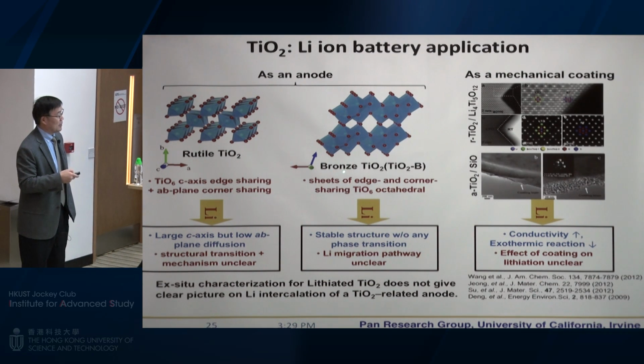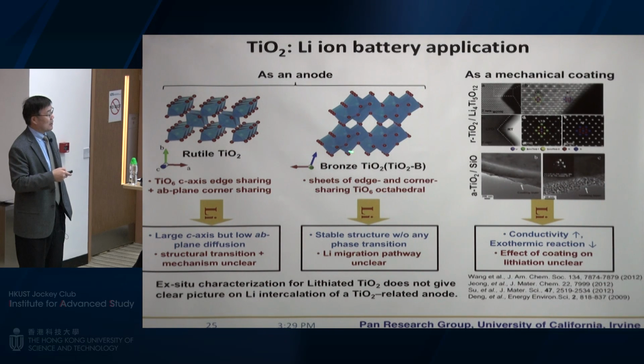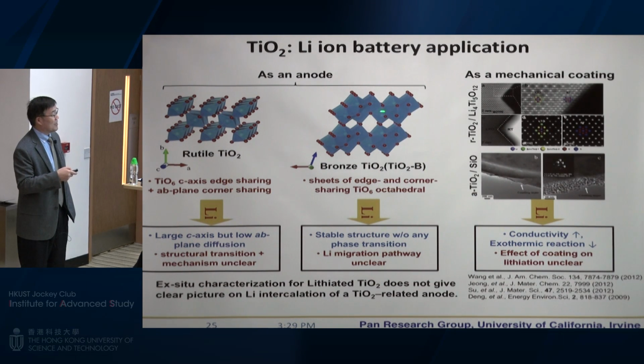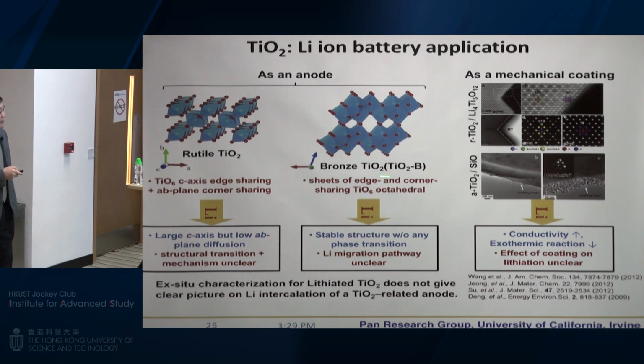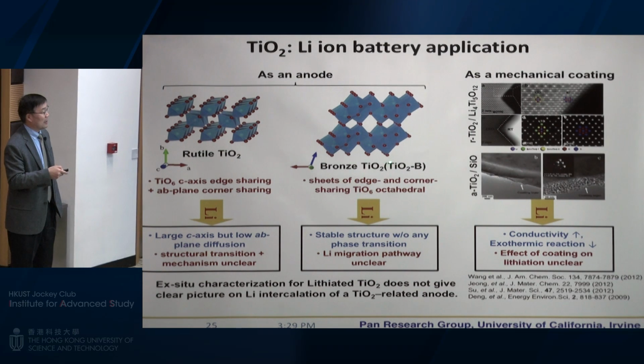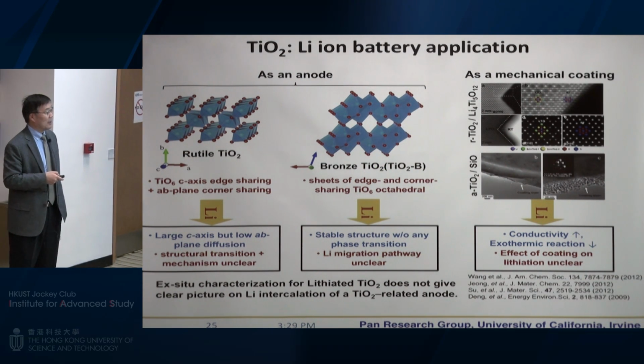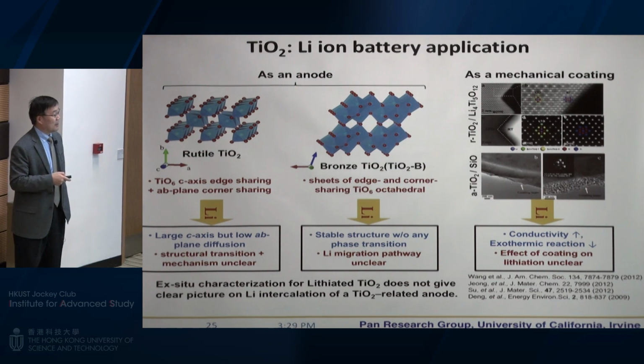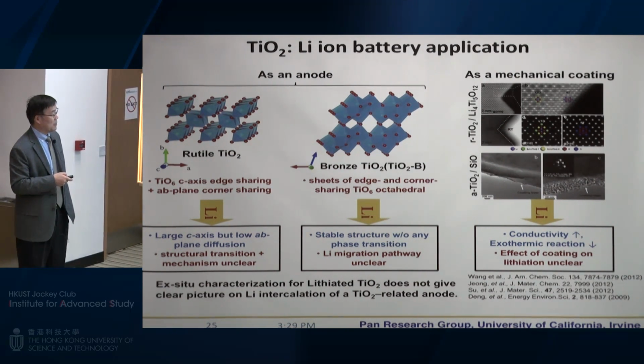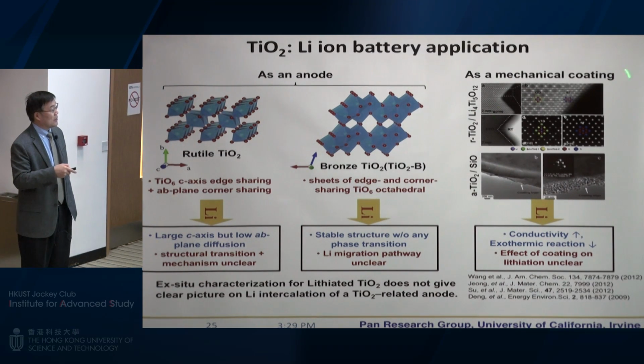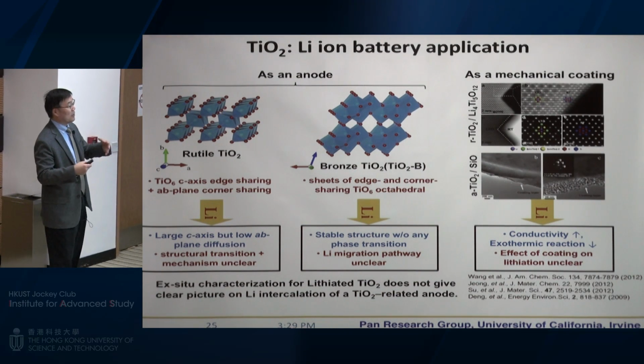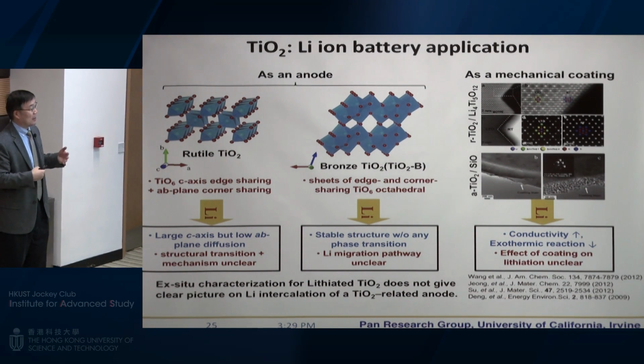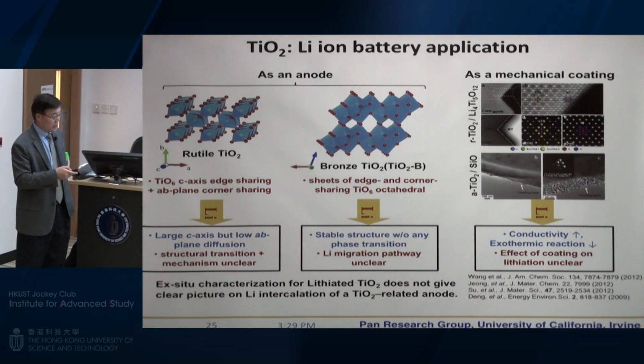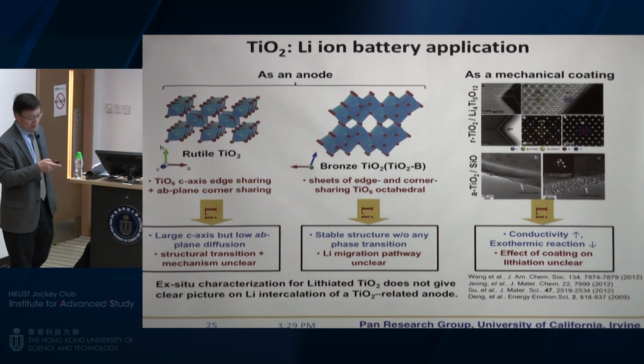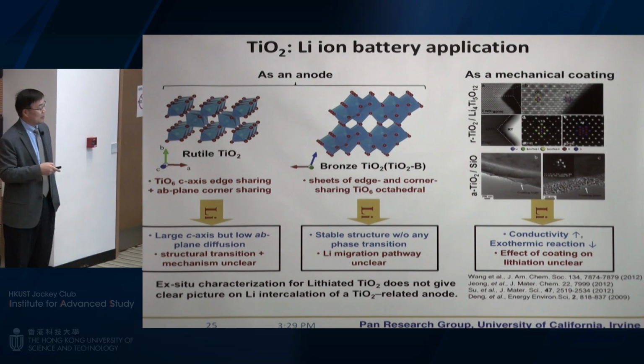So we actually developed a method to synthesize very high quality single crystal bronze-phase titanium oxide structure without using any water, so that you don't have a water-stabilized structure. And then we also studied TiO2 coated silicon wire, coated with oxide, and then see how this core-shell structure changes. I'm not going to talk about all of them. I'll just show you some examples. For those who are interested, we have published many papers on this topic, but then we can talk separately.